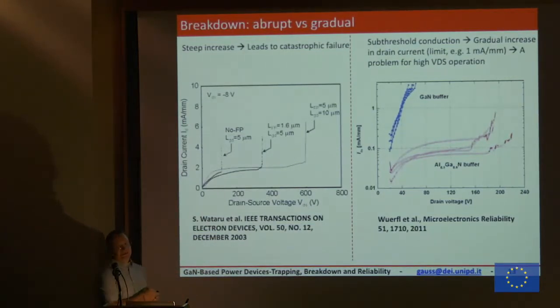In gallium nitride the situation is this: you cannot over-design a little, you have to over-design a lot. So for having a device working in a 600 volt system, you need a device with a breakdown that is 1000 volts or 2000 volts. Because you know that if for any reason during its life the voltage across the device goes close to the breakdown or at the breakdown, the device blows up. So this is the major problem. And still today, we don't have available devices with a sustainable breakdown. When they go into breakdown, they blow up.